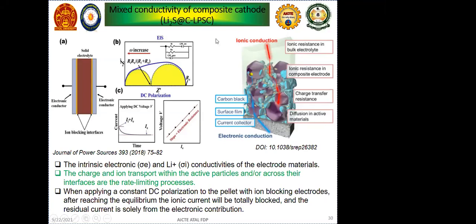Apart from that, when we mix some of the electrolyte with Li2S and carbon, the conductivity of the cathode also increases. It also suppresses the side effect, and there will be sufficient electrolyte in the system. So this is why we should really balance this Li2S and LPS system. It's really not that easy, because we have to try and try; many protocols have to be developed to get a proper ratio of Li2S, carbon, as well as LPS system.